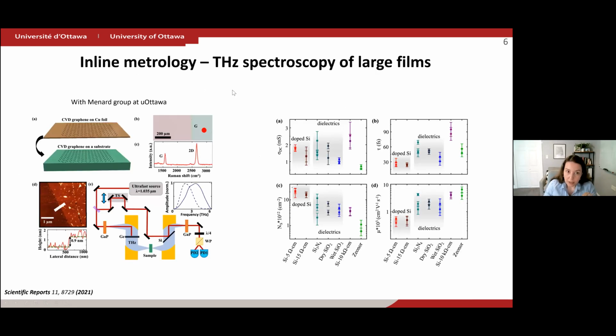And regarding inline metrology and finding ways that can assess the quality of a 2D material film, one thing we have used is, in collaboration with my colleague Jean-Michel Menard's group, a terahertz spectroscopy group. We've made these devices where CVD graphene, or graphene grown by chemical vapor deposition, was placed on different substrates that are of interest for the semiconductor industry. So we've used, as you can see here, silicon oxide, different preparations of silicon oxide, different resistivity for silicon, as well as certain polymers and silicon nitride. And so we've explored using the terahertz spectroscopy signals. We've explored the electronic quality of the films depending on the substrate that they have, and we try and understand the differences between the different substrates. But nevertheless, this entire work demonstrates that terahertz spectroscopy could potentially be a good way to incorporate it into the inline metrology of 2D materials.